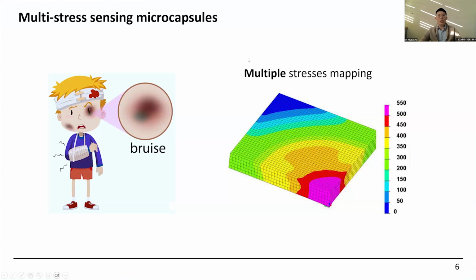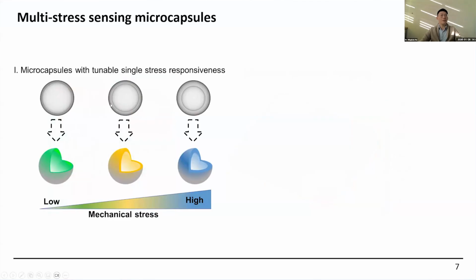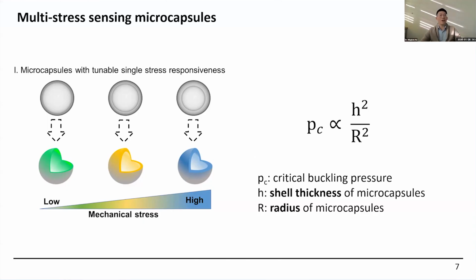We know the real environments are more complicated than just one type of damage. So we ask ourselves, can we make a system that can sense multiple stresses at once, or simultaneously? To do that, we further developed our microcapsule systems. The breaking of the microcapsule depends on the shell thickness as well as the diameter of the microcapsules. If we have a thicker shell, then it's harder to break. With that, we can tune the breaking force of our microcapsules. Then we can encapsulate different dyes inside to show different signals depending on the different breaking forces.